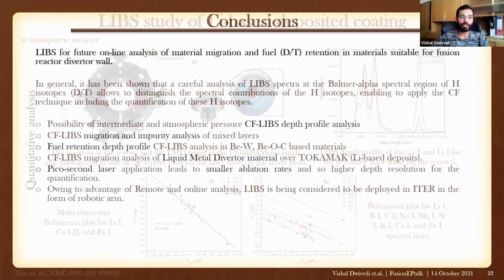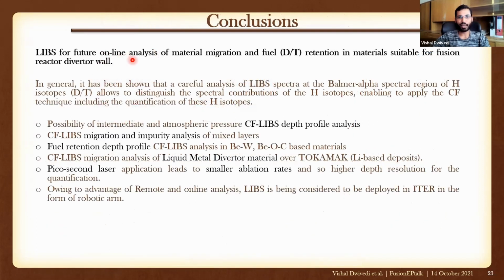So conclusion, LIBS is suitable for future online analysis of material migration and fuel retention in materials suitable for fusion reactor divertor. In general, it has been shown that the careful analysis of LIBS spectra at the Balmer alpha line near the H alpha line, deuterium tritium, allows to distinguish the spectral contribution of the hydrogen isotopes, which is deuterium and tritium, enabling to apply the CF-LIBS technique, including the quantification of these hydrogen isotopes.